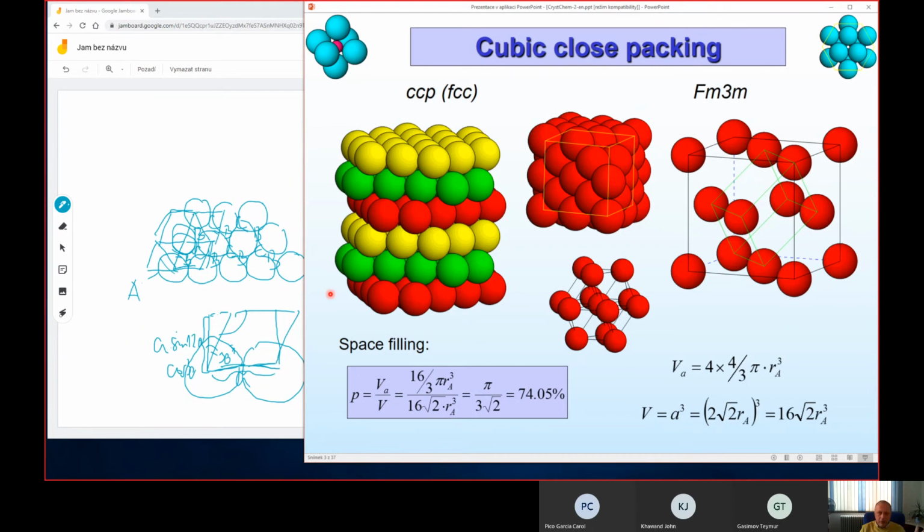But the cubic unit cell is a particular case of a rhombohedral unit cell where the alpha angle is 90 degrees. So this direction corresponds to the diagonal of a rhombohedral unit cell, but in this case, because of the close packing, it is the cubic unit cell.